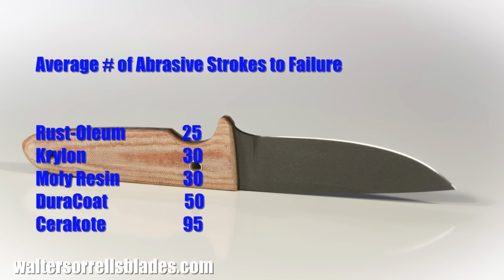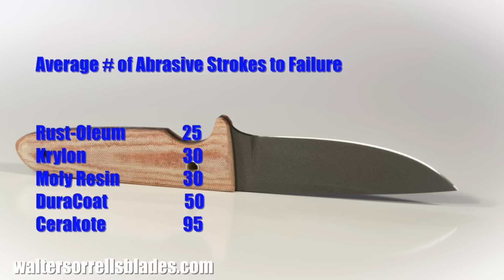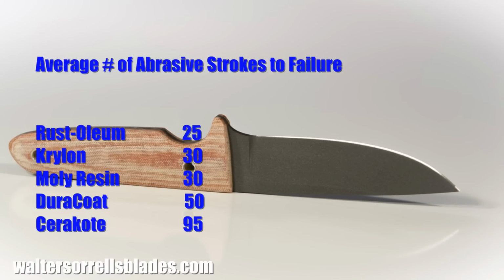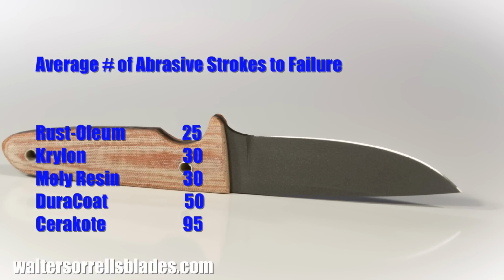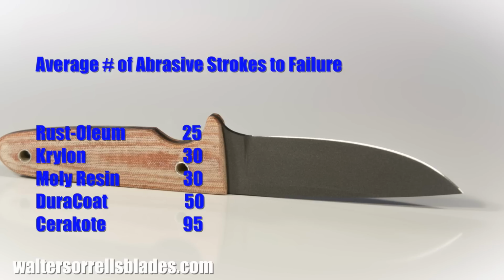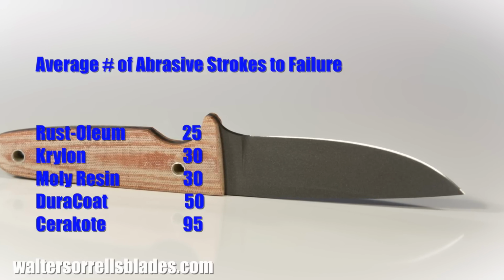I'm going to make some excuses for Moly Resin. First, as I said, it was applied very thinly. There's a shelf life to this product, and it was reaching somewhere near the end of that shelf life, so maybe I was being unfair to Moly Resin. Or maybe not. Bottom line, performance of the sample that I used here was not so impressive. It averaged around 30 strokes before it gave up.